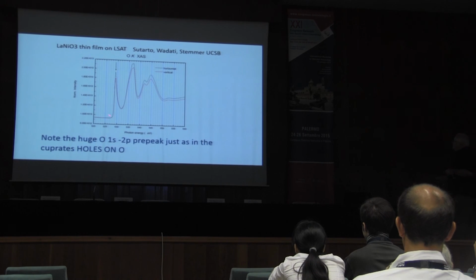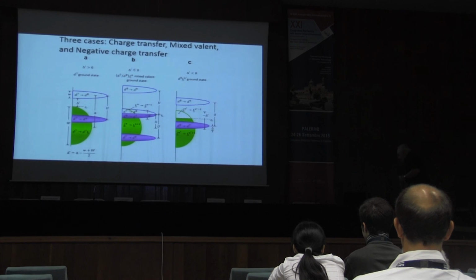And there again, you see this now in a pure material. So now I'm not doping. I'm now looking at the pure material. And you see this extremely strong narrow pre-peak over here in the oxygen edge, indicating again that the holes are mainly on oxygen. Now, then you have a real problem as to how to describe it.